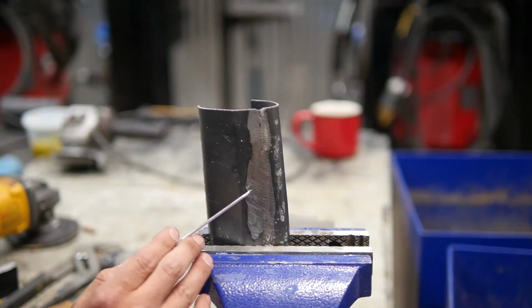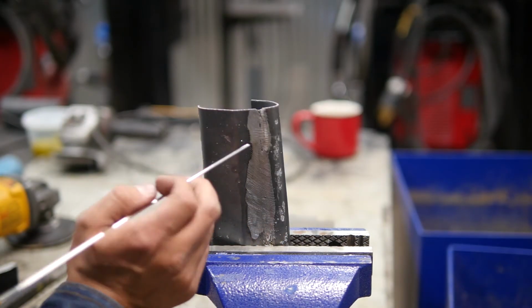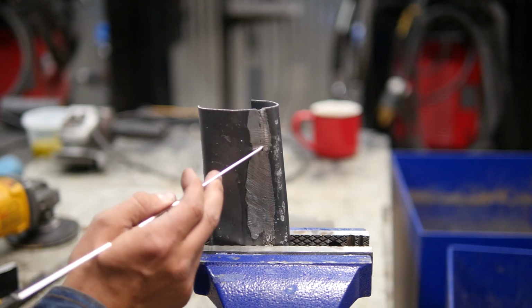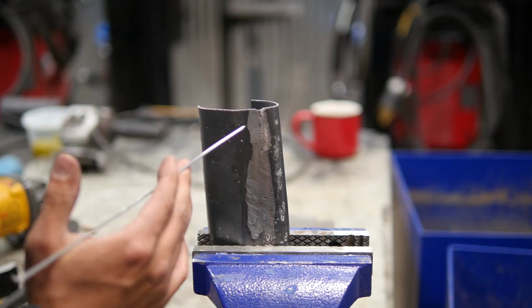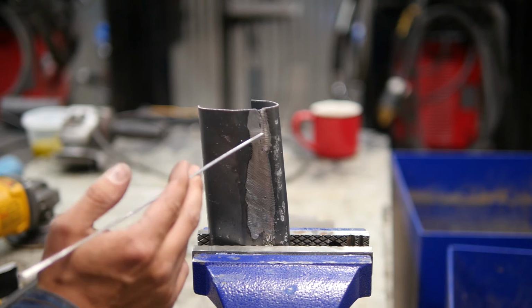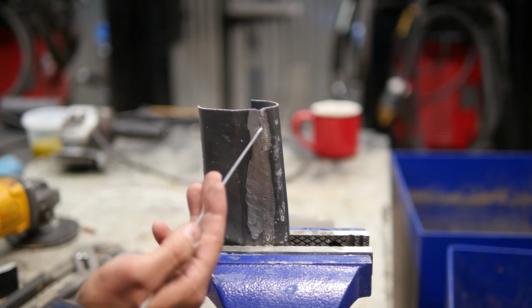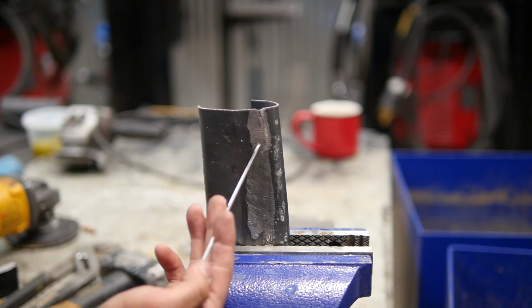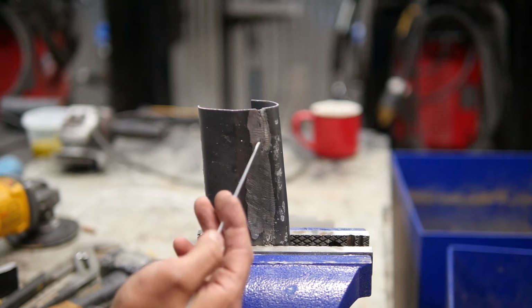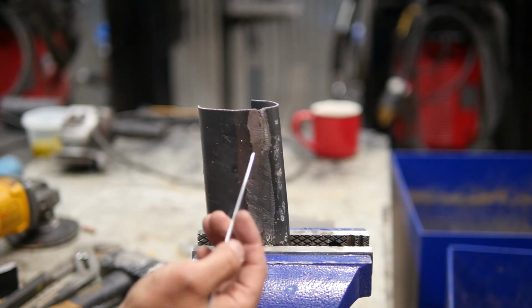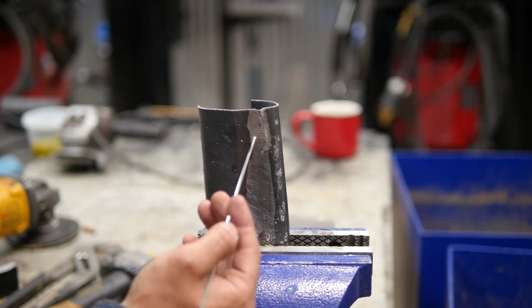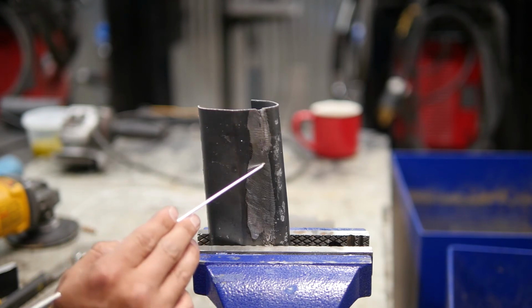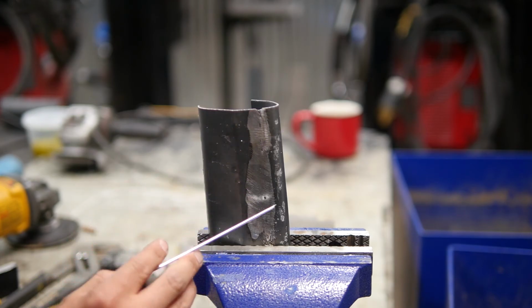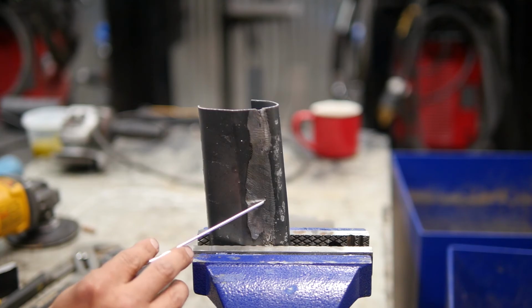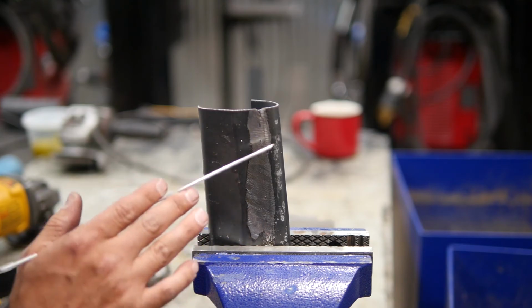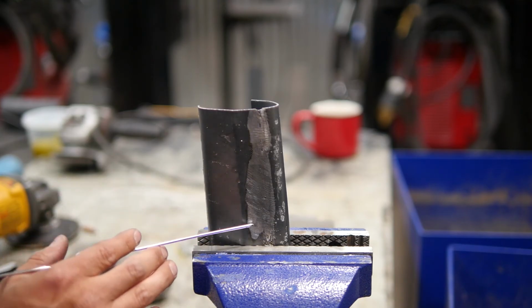Now we have our sample ground flush, and you can clearly see the first weld that we did with the higher procedures, that was 70 inches per minute at 15 volts, it trapped a lot of slag. All these little pockets are slag and places where the slag kind of popped open and left these ugly holes. But when we turned the procedures down and got a smoother weld, I did have one little pinhole right here, but that would be pretty easy to fix. But the rest of the weld stays pretty smooth.